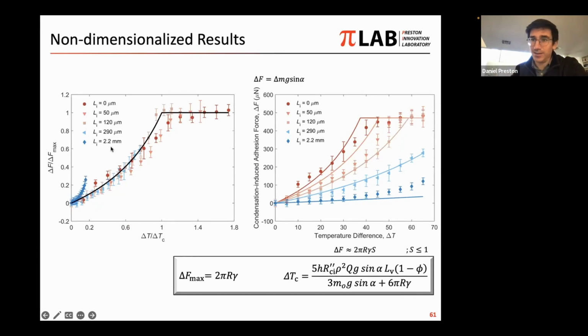This is the thickest insulating layer. Our model right now has the assumption that as thickness goes to infinity, there would be no heat transfer, and it totally neglects the thermal mass of the coating itself, the insulating layer itself. That's what we hypothesize as the reason why there's some disagreement as we go to very thick insulating layers.